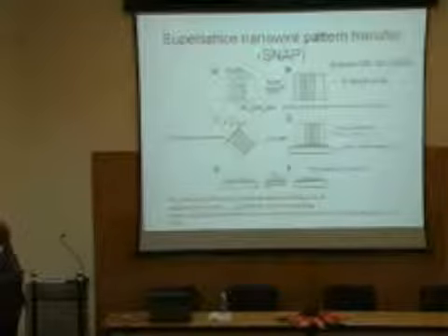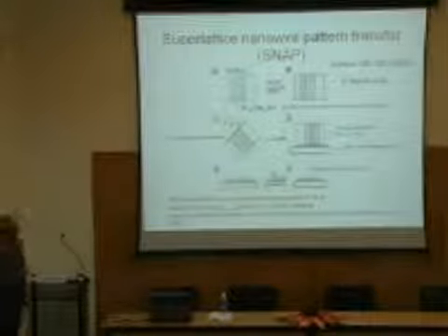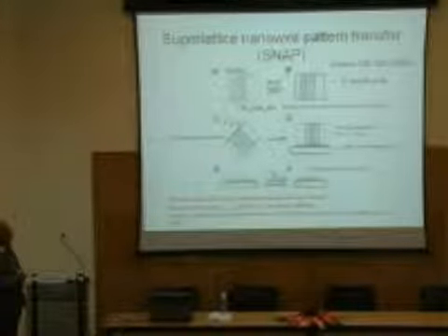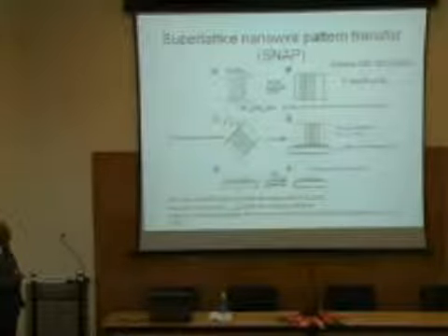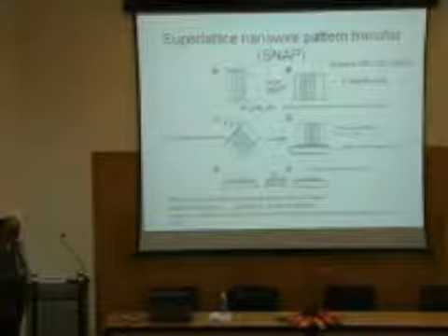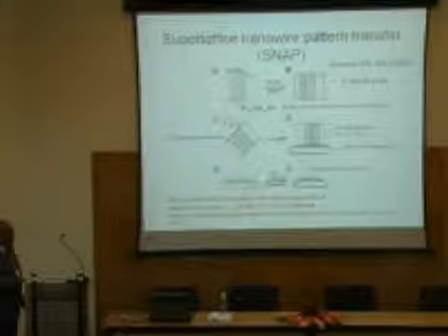In this example, you have a gallium arsenide substrate, and on that you have some aluminum gallium arsenide semiconductor, and then you etch it in such a way that part of it goes away, so the top part is exposed, and then you can remove that gallium arsenide by some chemical methods, and after that you can transfer it onto a silicon substrate.